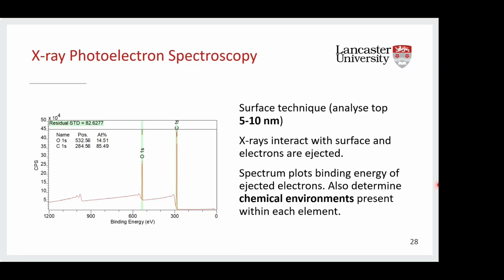You can use X-rays of a known energy and direct them towards your surface. Then electrons will be ejected, and you can calculate the binding energy of these electrons. So the binding energy of the electrons depends on the core level from which they're excited. Hence, you can sort of work backwards and determine the elemental composition and also the chemical environments for each element.